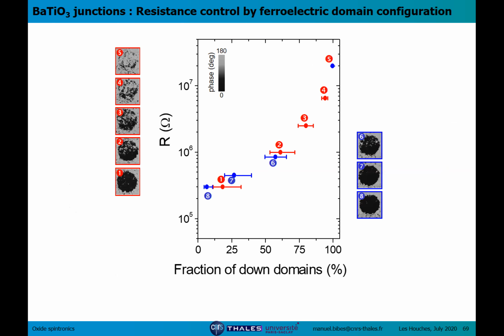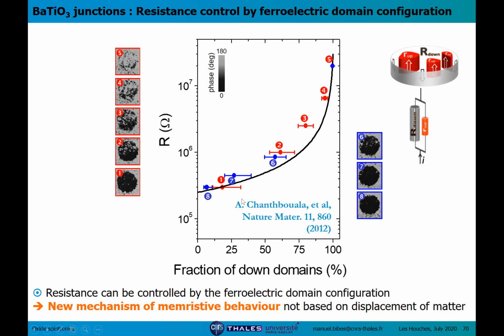So there seems to be a clear connection between the resistance value and the domain population, so we can analyze this. We can extract from the images the fraction of down domains and plot the resistance as a function of this fraction. And we see that we have a nice systematic trend, which we can even fit with a very simple model, considering that up and down domains have different specific resistance, and only the relative area of one with respect to the other is setting the resistance of the device. So this provides a new mechanism for memristive behavior, which is based on ferroelectric domain switching and not based on oxygen vacancies or defects.